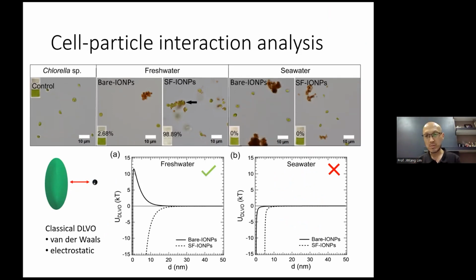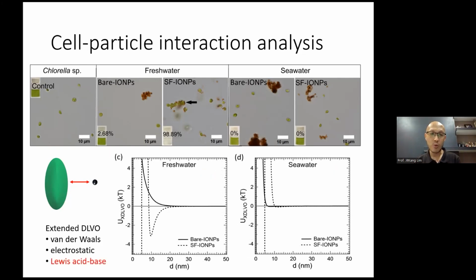So after some studies, we realized we were missing one key interaction between the particles and the cell, which is called Lewis acid-base interaction. By incorporating Lewis acid-base interactions into the entire model, and by repeating the calculations, our mathematical model can now successfully predict that under seawater conditions they have a huge repulsion, mainly because of Lewis acid-base interactions. And this is actually preventing the iron oxide particles, even though they are coated with PDDA, and supposed to be electrostatically attracted to each other, but because the Lewis acid-base interaction is so strong, it prevents the attraction from happening.